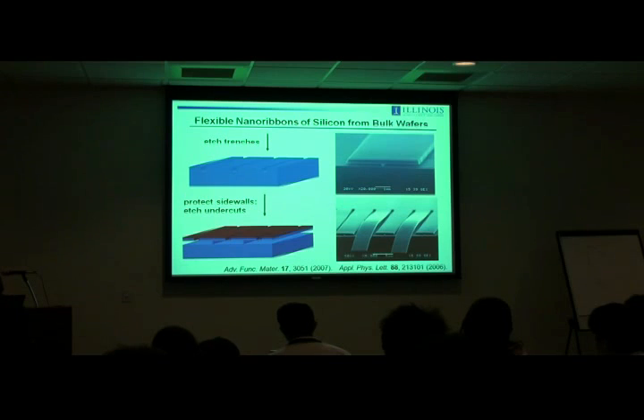And the first idea is based on elementary bending mechanics, which dictates that for a given bend radius, the maximum strain in the material decreases linearly as you decrease the thickness. That's it. So a 2x4 is not flexible. The sheet of paper is the same material essentially, but just by virtue of the fact that the paper is thin, it's bendable. So the same elementary mechanics applies to silicon. So if you can take a bulk wafer, which might be 0.5 millimeter thick, and slice it very, very thin, then the silicon becomes flexible. And so there are ways to do that.